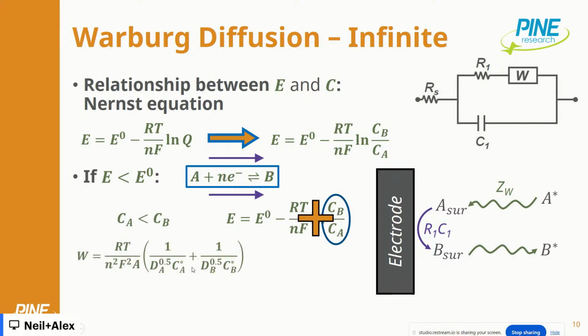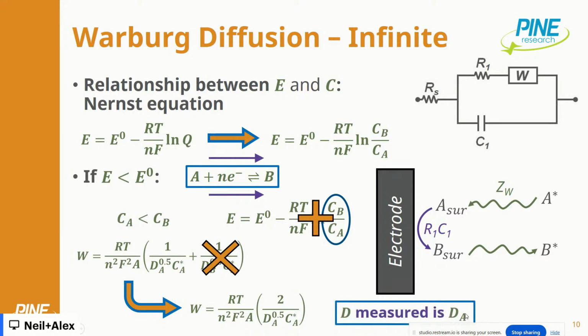What does that mean here? Well, it's sort of counterintuitive. If the concentration of B is greater than A, we can neglect it because it's 1 over, right? CB is in the denominator. So the bigger the denominator is, the closer to 0. 1 over a large number is 0. So this goes away, and we can simplify it to basically being here. So one way to look at this is that if we are reducing for our standard process at a reducing potential, then we are measuring the diffusion coefficient of A.